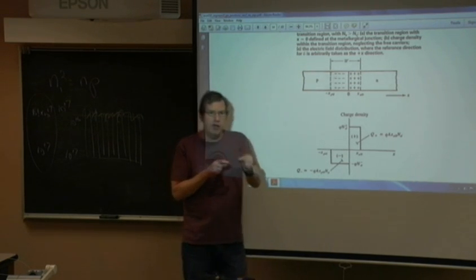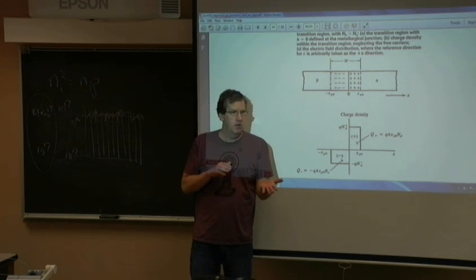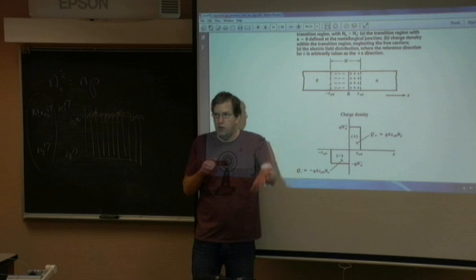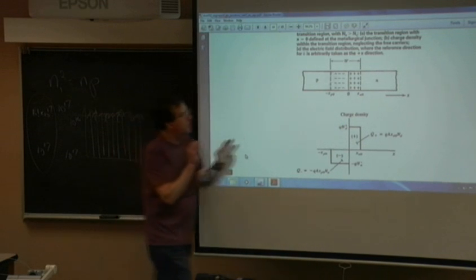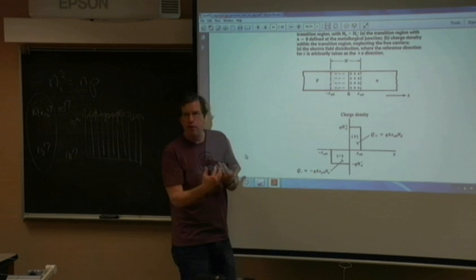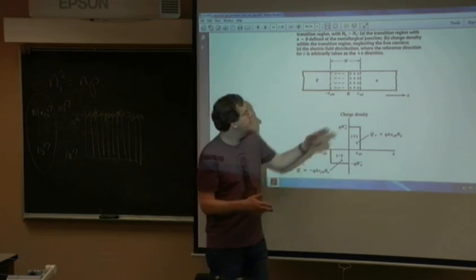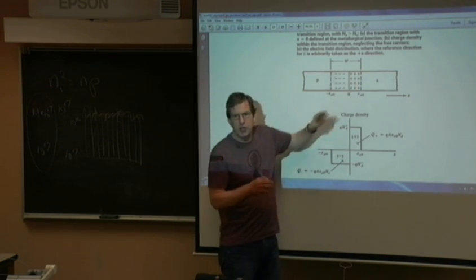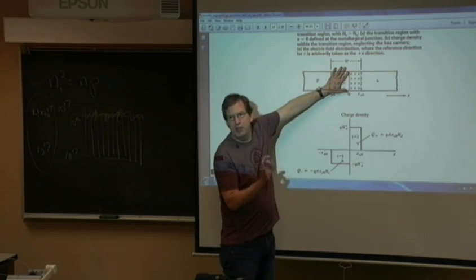And remember, what were some of the temperatures you guys used? 900? Yeah. So it's not going to move at 300. I had to take it up to 900 to get that phosphorus to move. So the phosphorus is immobile. It's tethered by 4 covalent bonds to 4 silicons. And so the ionized donors are spatially separated throughout, forming our magical depletion region.